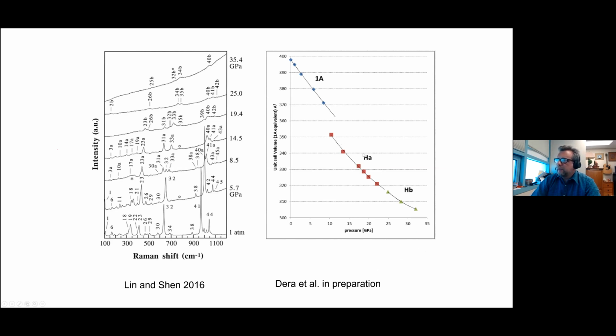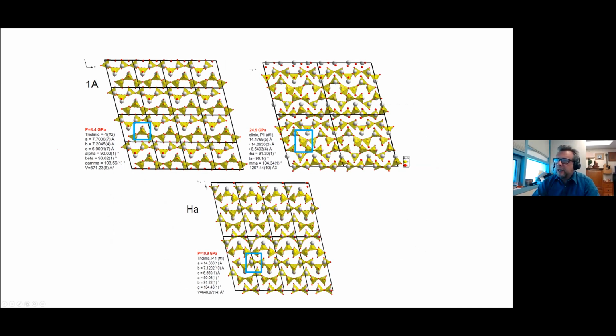We call these 2 high pressure phases Ha and Hb. And then if you look at what happens with the crystal structure, the first phase change is just a change in the kinking angle of the tetrahedra, doesn't affect the coordination number. So this is similar to the first phase transition that we observed in orthopyroxene in enstatite. The second phase change, again, analogical to orthopyroxenes, has one of the many symmetry-independent silicon oxygen tetrahedra turn into a 5 coordinated site now.